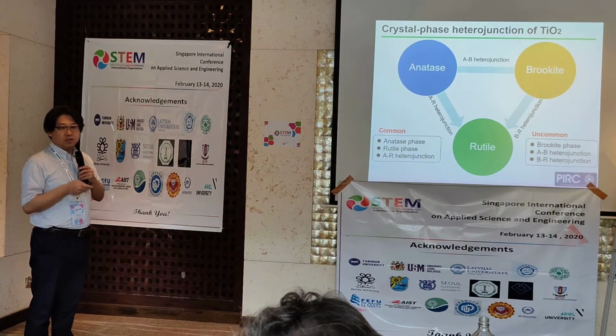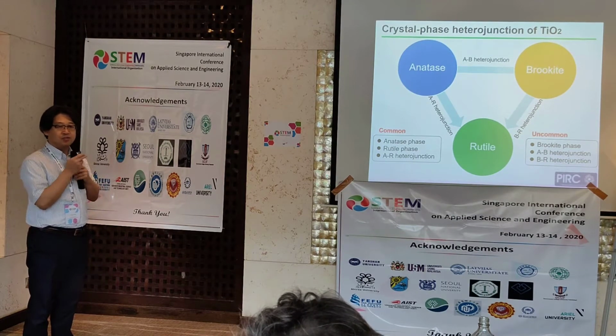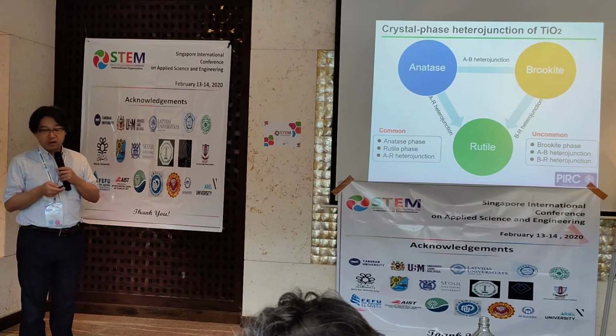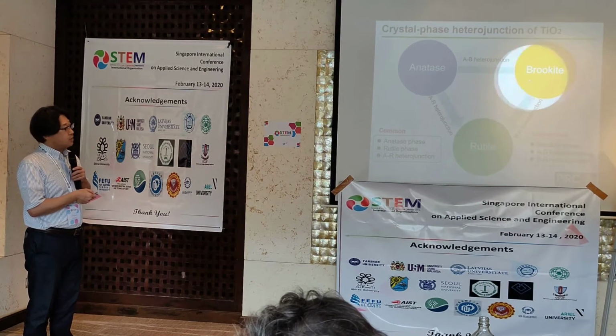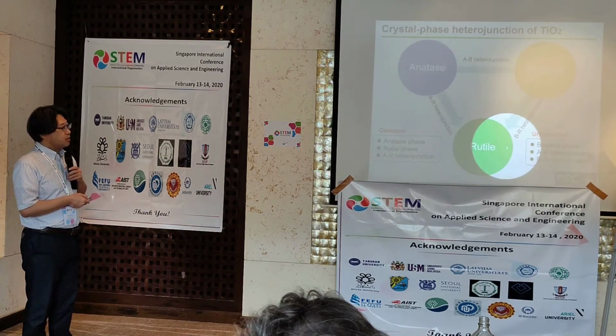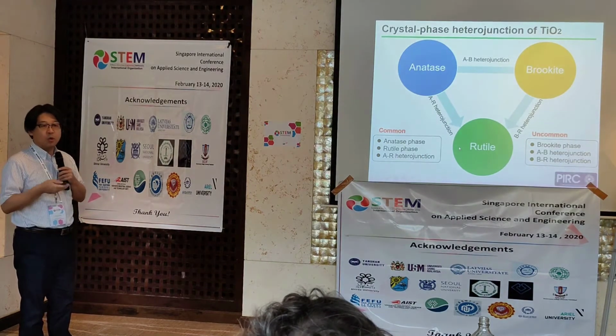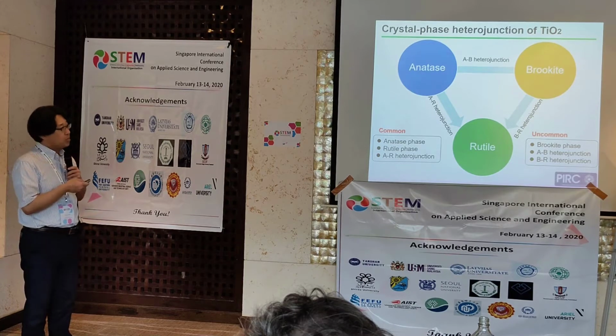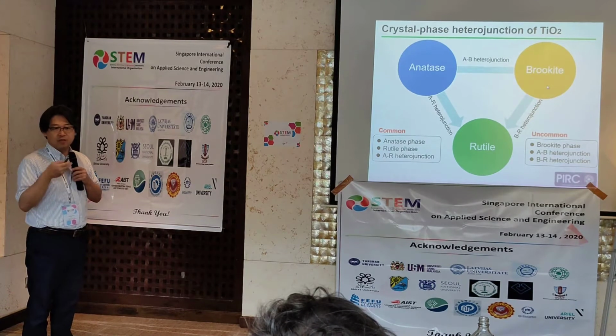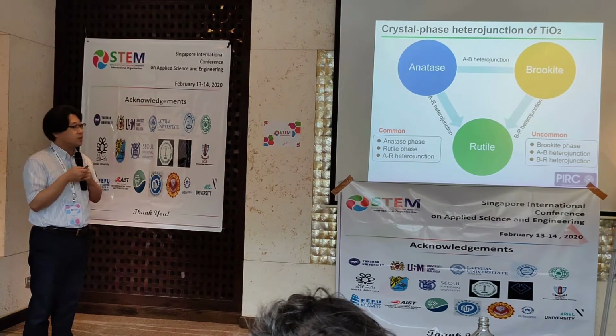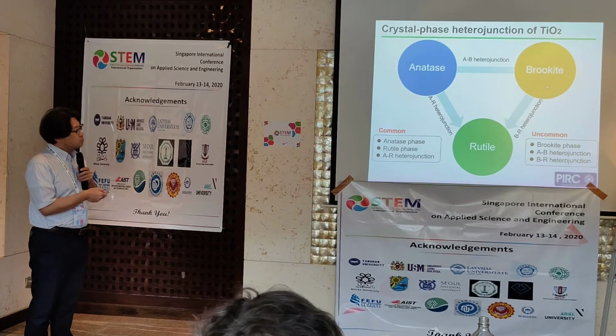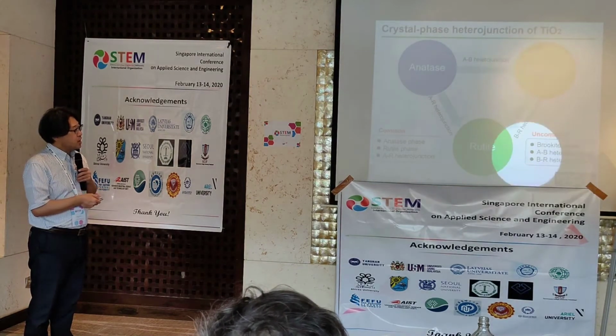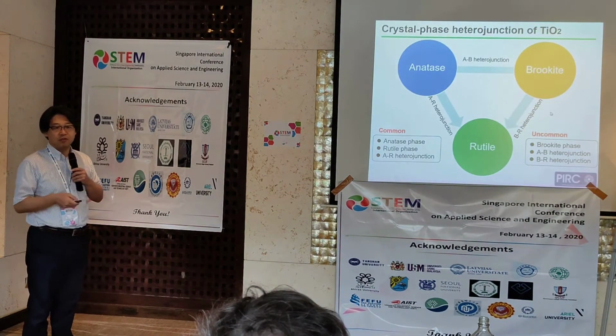So in the case of titanium dioxide, we know the three major crystal phases: anatase, rutile, and brookite. The anatase and rutile combination, the AR heterojunction, is a common material and is already commercialized. But brookite is a rare material, and it is difficult to make the brookite structure of titanium dioxide. The combination AB heterojunction and BR heterojunction is also difficult to make